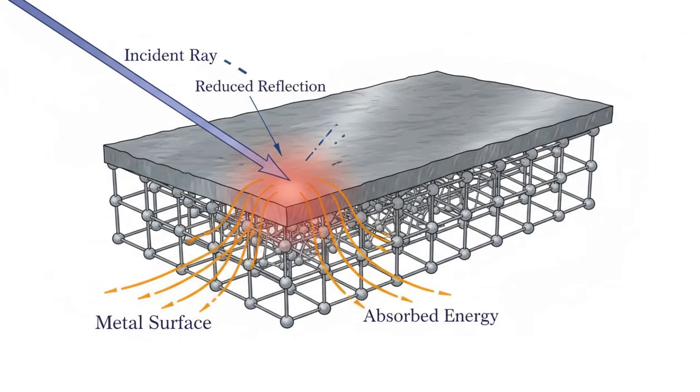Start with absorption and reflectivity. Only part of the beam couples into the metal. Highly reflective surfaces return energy. Oxides or coatings can increase absorption. Add thermal conductivity. Metals like copper and aluminum pull heat away quickly. That lowers the local temperature rise and limits depth. Consider heat capacity, density, and phase change. You must apply energy to heat the metal, to reach the melting point, and to cross the latent heat barrier.